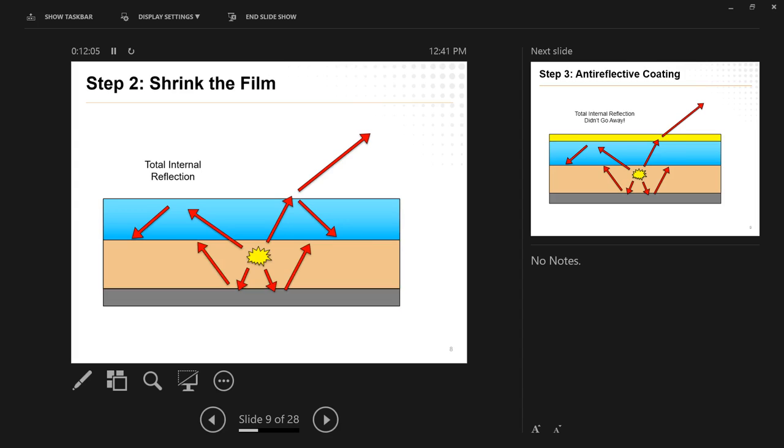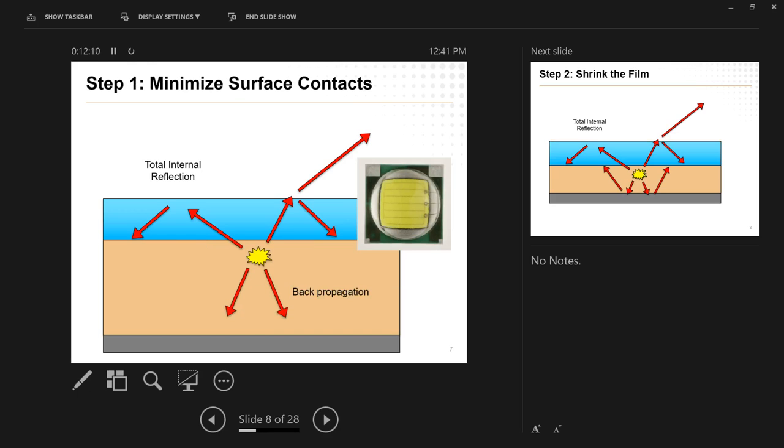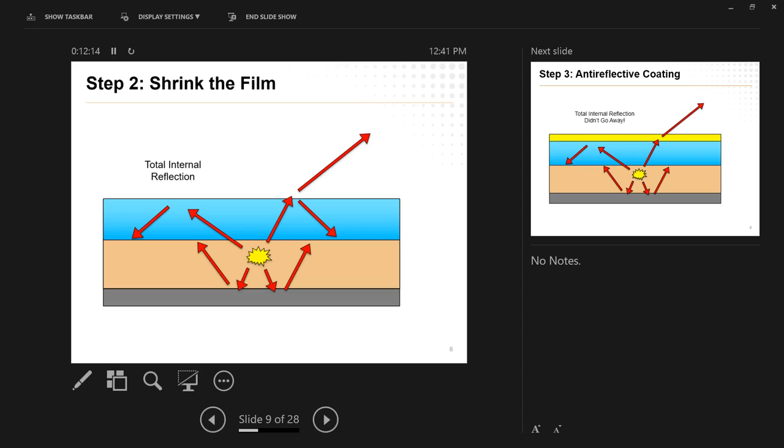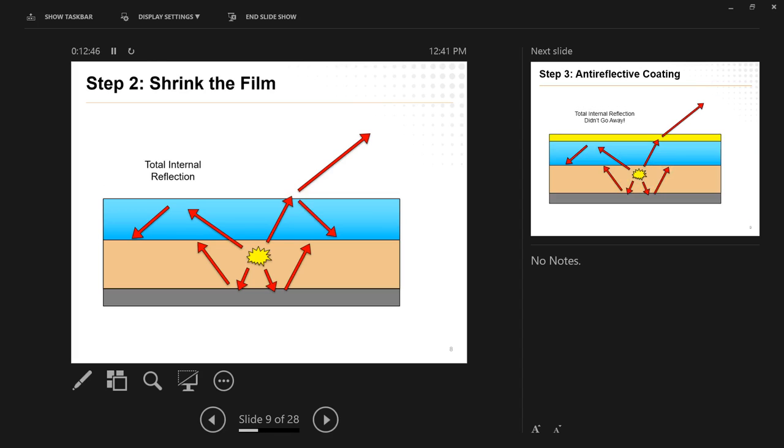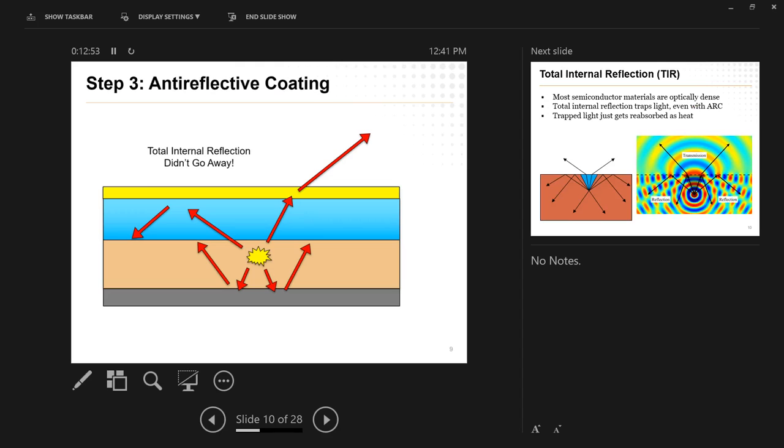So right there, we have kind of this opposite thing. Remember, with solar cells, we want it to be very thick. That's because we wanted to trap light. So now if we want light to not get trapped and get out, we just do the opposite and try and make them very thin. The last problem, though, is this idea of... Actually, there's two more problems. So the next problem, we have Fresnel reflections here. So a photon will come up, hit the boundary, and a little bit of it will reflect while a little bit of it transmits through. So that's not too bad. You just add an antireflective coating. But then we still have this other problem over here of total internal reflection. So fun fact, an antireflective coating will minimize Fresnel reflection, but it will not do anything to stop total internal reflection. So that ray here going up and back down again is completely unaffected by the antireflective coating. So that creates a very difficult challenge.